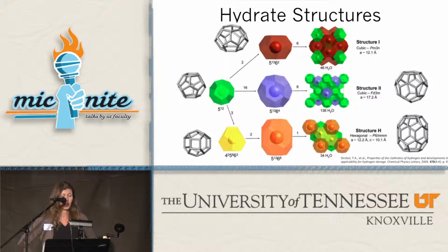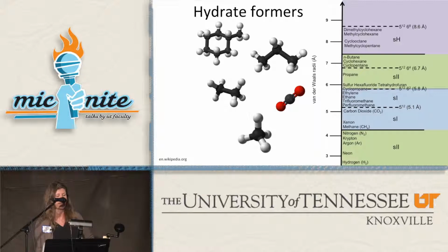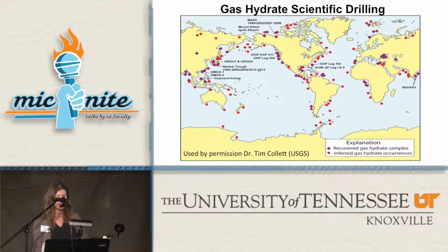The hydrate structure is made up of different polyhedral cages. Both methane and carbon dioxide hydrate form structure type 1, made of 2 cages consisting of 12 pentagonal sides and 6 cages made up of 12 pentagonal sides and 2 hexagonal sides. A variety of guest molecules can be occluded, including methane, carbon dioxide, ethane, propane, hydrogen, and hydrogen sulfide. Interestingly, both methane and ethane hydrate alone form structure type 1, but when combined, they form structure type 2, illustrating the complexity of the host-guest interactions.